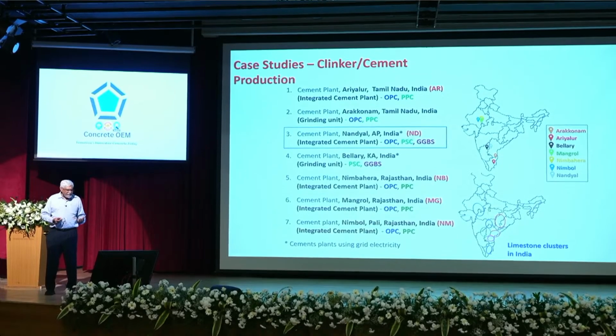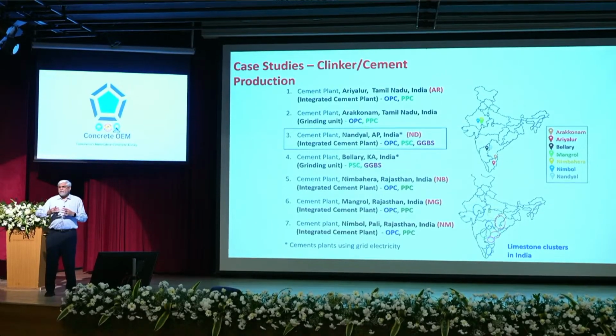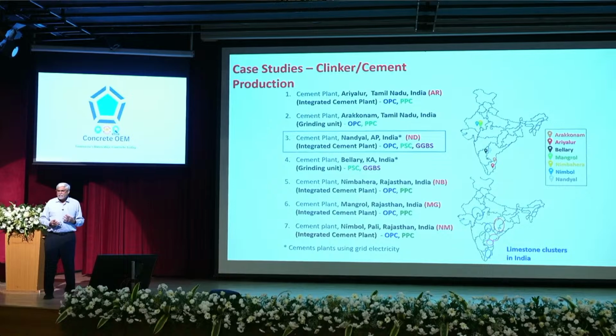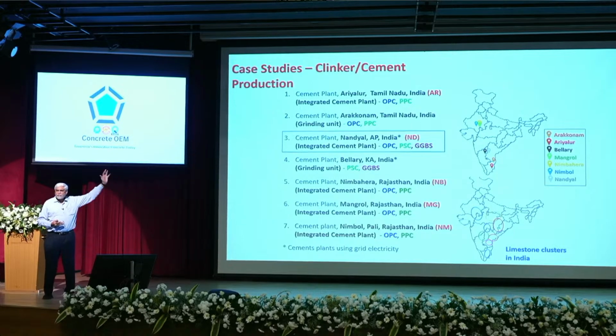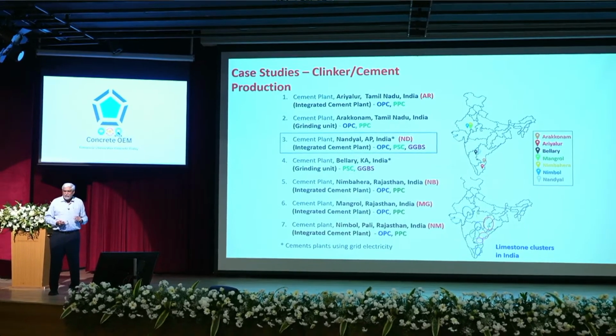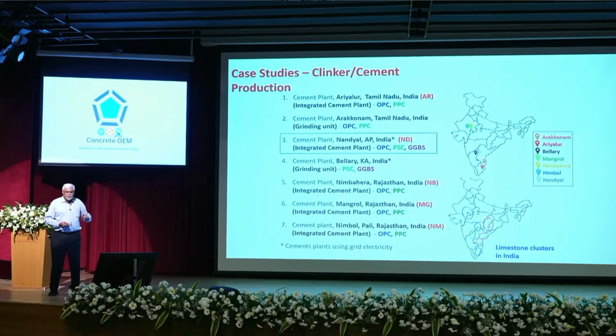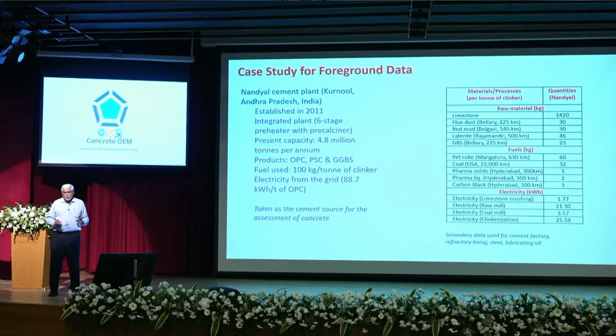So what we did is went to different plants. I'm showing you this. It represents the different clusters, limestone clusters. I'll show you the results of one plant in Nandyal. So we go to the plant and ask them, what are all the things that went into your cement and clinker? For a ton of clinker, ton of cement, what are all the materials which go in? And we find things which are not there in textbooks. We find a lot of cases, or most cases, that there is no clay added to the raw meal when you have,